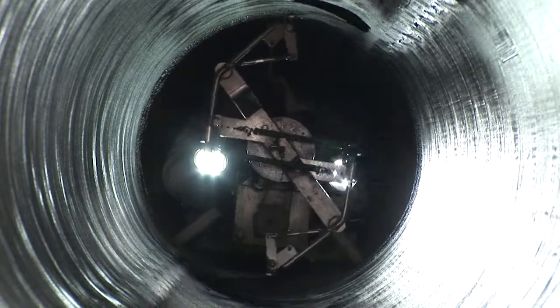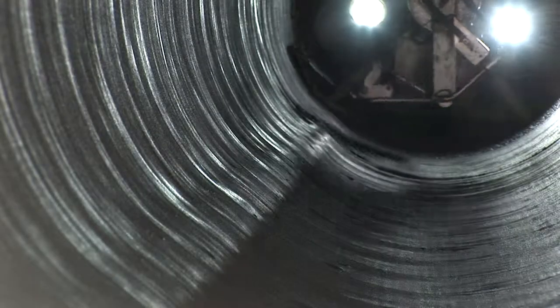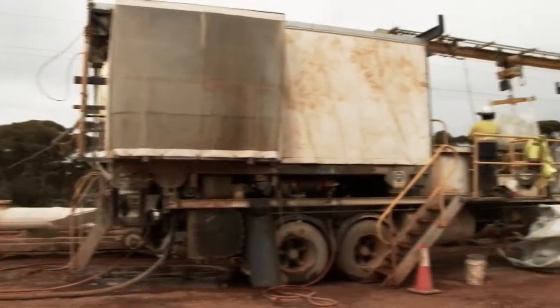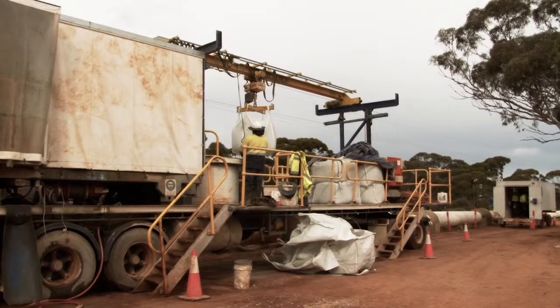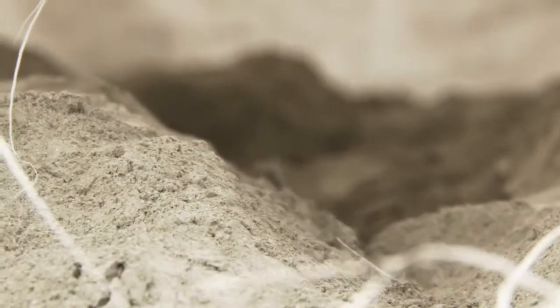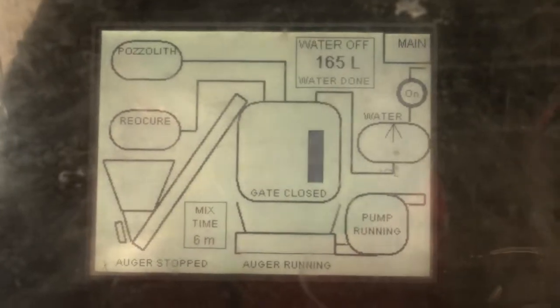A man-operated relining machine then centrifugally applies fresh cement mortar lining to the inside of the pipe at a consistent thickness. This machine uses an automatic rotating trowel mechanism to produce a smooth surface finish. An external mixing plant stationed at the equipment access point provides the mortar for this process. 1-ton bags of specially pre-blended sand and cement are mixed in a planetary motion pan mixer with automatically measured amounts of water and other additives.